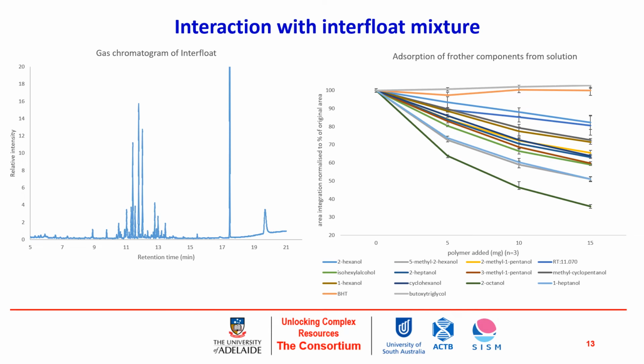Now, one thing of note here is there are far more contributing components to the interfloat mixture beyond that of what is simply reported as the active constituents on the bottle. Taking that into consideration, I used mass spectral analysis to identify many of these components, and I named them and looked at how they were stripped or removed from solution with increasing addition of polymer. This is what I'm showing on the right-hand side of this slide, where as I incrementally increase the amount of polymer sitting in these aqueous solutions of interfloat, more and more of these components are being removed, but only those that are hydrophobic and specifically in order of their hydrophobicity. And this is helpful because it does confirm that the cyclodextrins are behaving the way that we want them to.